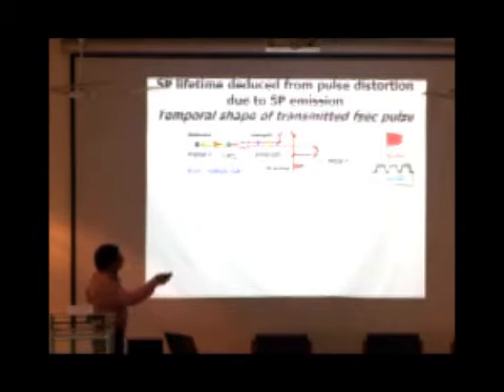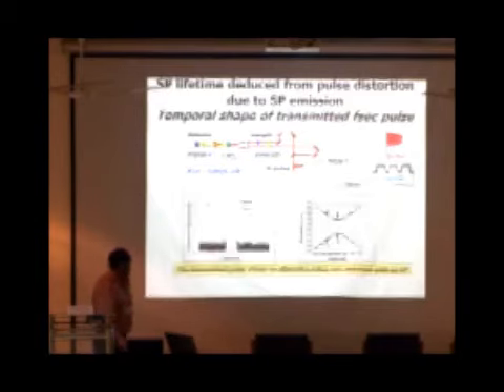So we do the time resolved transmission measurements to resolve this pulse shape. What we see is that when the pulse is non-resonant with your plasmon - for example, if you look at the dispersion, you choose a wavelength where we are not exciting any plasmons, like 780 nanometers in this case.